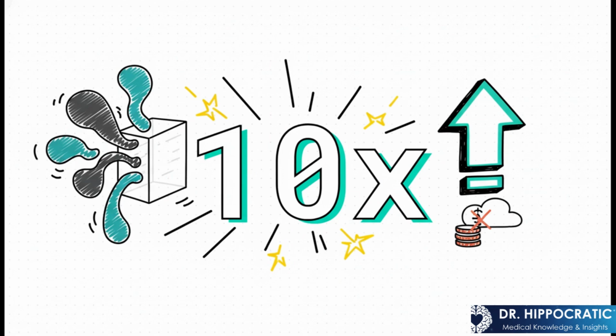One incredible solution involves adding elastomers, which are basically rubbery materials, into the acrylic. And get this, it can increase the impact strength by almost 10 times. That's a massive improvement. So what's the catch? Well, these high-performance materials are often way more expensive, and that's really limited how much they're used.